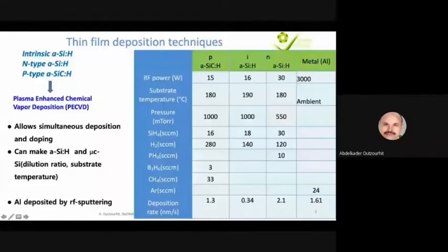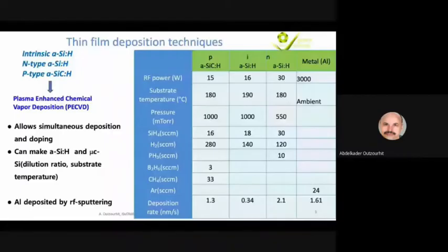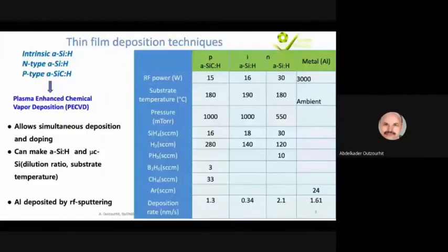And mainly the dilution ratio, which is the ratio of the hydrogen to silane. This ratio governs the structure of the deposited silicon thin films, in addition to the substrate temperature, and of course, the RF power of the plasma. Also, the aluminum back contact is deposited by radio frequency sputtering, and the deposition parameters are shown in this table for both the three amorphous silicon layers and also the metal.